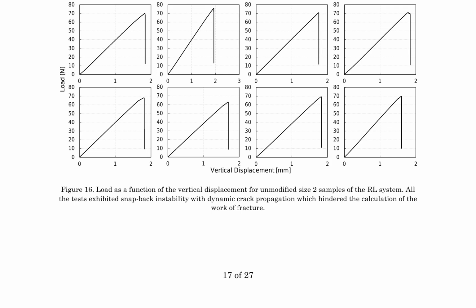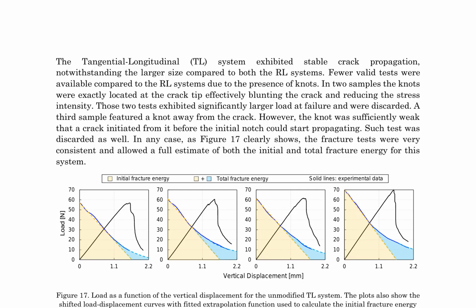In contrast, the TL system demonstrated stable crack propagation, despite its larger size compared to the RL systems. However, fewer valid tests were available due to the presence of knots. The fracture tests were very consistent, allowing for a full estimate of both the initial and total fracture energy for this system, as shown in Figure 17.